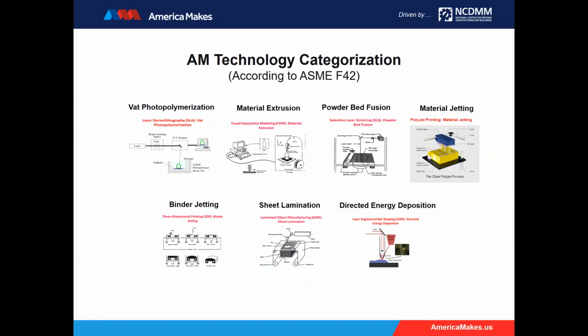The powder bed fusion is a very popular process where the powder is in a bed, and they use a laser. It could be a CO2 laser, it could be an Nd:YAG laser, could be even an E-beam to melt the layer according to the cross-sectional geometry. And every layer, you put another layer of powder, and then you have the roller spreader to flatten the surface and add another layer. And depending on whether it's based on laser or E-beam, the process could be selective laser sintering, usually for thermoplastics, or selective laser melting for metals.